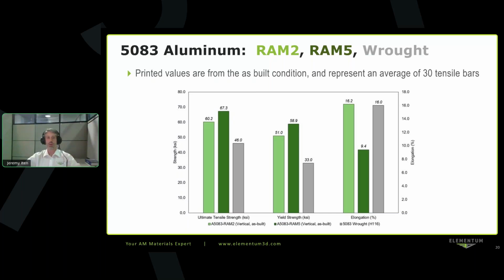And actually, if you do a stress relieve on these printed materials, it maintains essentially identical strength. You don't see a strength drop in this material, even with the stress relief, which you would typically see from other printed materials. So the strengths from both the RAM 2 and the RAM 5 are much higher than the legacy wrought product, even though the wrought product is in a strain hardened condition. Elongation of the RAM 2 is essentially equal to the traditionally produced wrought product. The RAM 5 does have a little bit of decreased elongation, but still a 9 or 10% elongation is still a healthy elongation for an aluminum alloy, with the strengths being a good 50% higher or so than the strain hardened wrought produced product.